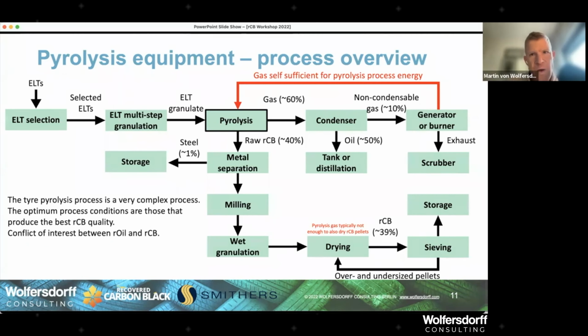Steel is cooled down in a controlled way to maintain certain properties. Now, if you heat up again, that changes the structure of the steel, and it has less value. How much? I would say half the value really of that 200. So maybe heat-treated steel, you would get closer to $100 per ton, and mechanically separated 200.